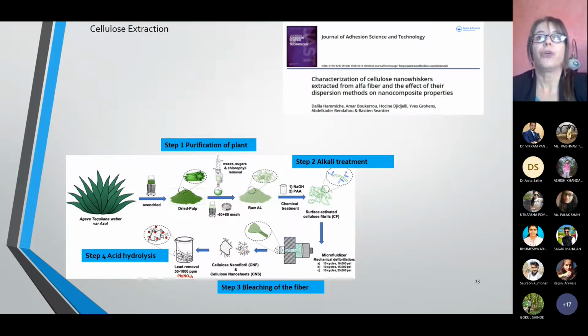And the isolation of the cellulose fiber. The second step is controlled chemical treatment to remove the amorphous region of the cellulose polymer, because cellulose has crystalline region and amorphous region, and it is more interesting to remove the amorphous region and leave only the crystalline region. So the first step is the purification of the plant to obtain the pure crystalline fraction from the pretreatment of the selected natural fibers. Fibers are first washed with distilled water several times, dried and chopped.